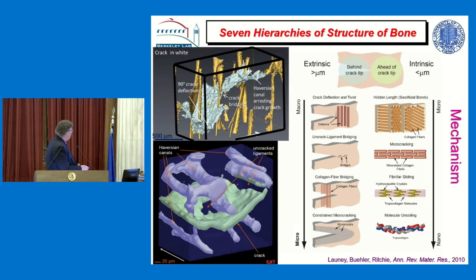So we can see this. This is computed tomography in the synchrotron. These are the osteons. Well, you're actually seeing the Haversian canals almost, but they have mineral along the interface. The white region is the crack, and the crack deflects as it encounters these osteons. It also twists. And that can give you maybe a factor of two or more increase in toughness.